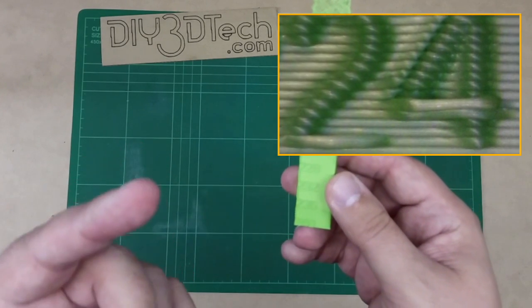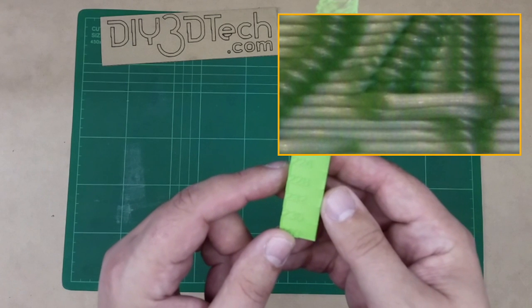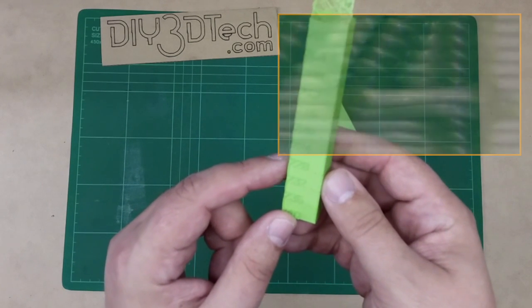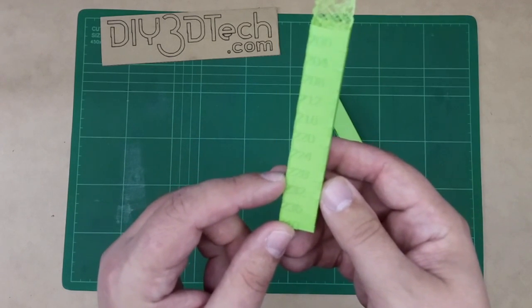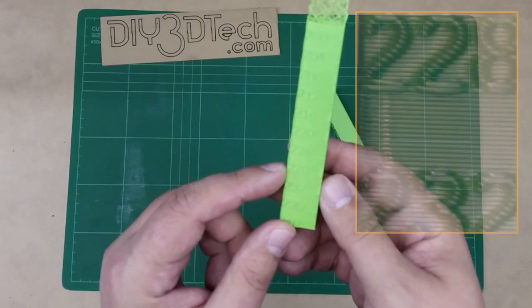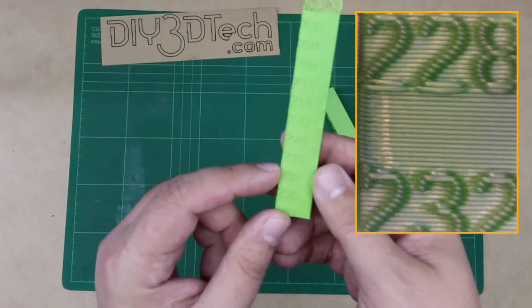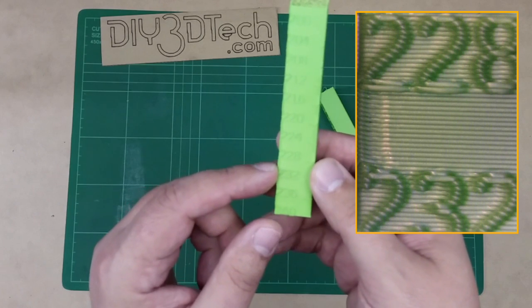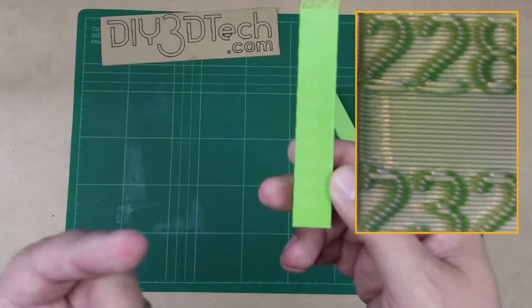At first when I looked at it, I thought 224 was about the sweet spot when looking at this. However, what I did is I put this under the USB microscope and took a little bit closer look. And what I determined was actually a temperature range probably closer to about 230, 228 to 230, on the Monoprice was a little bit better.